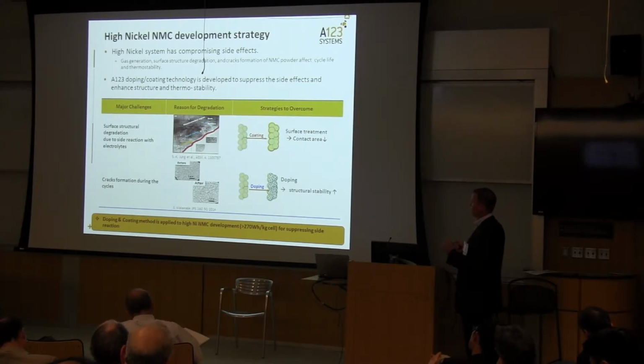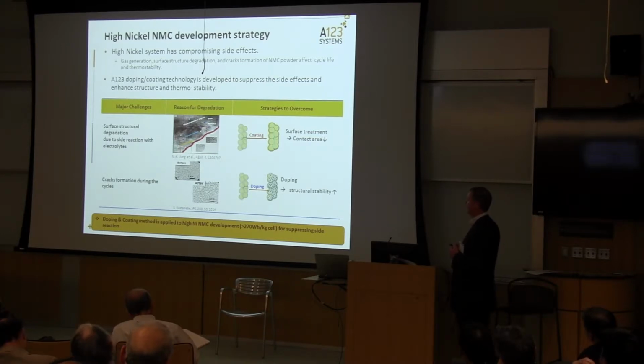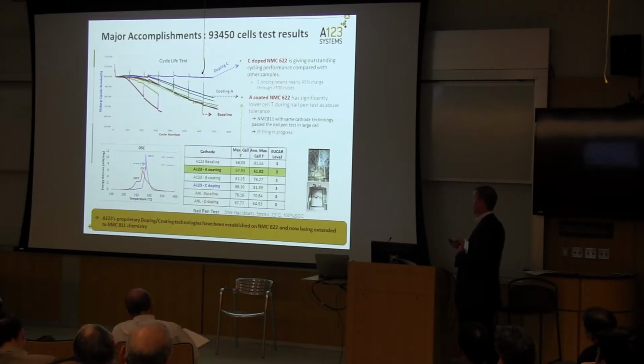And then also, as John Marie talked about this quite a bit, interfaces are key in this. And so, especially when you start to get to 60, 70, and 80% nickel, you really have to control the interface of the particle, both at this primary and secondary level, because those interactions with the electrolyte can actually drive some of these reactions that either hurt the performance from an electrochemical standpoint or from an abuse standpoint.